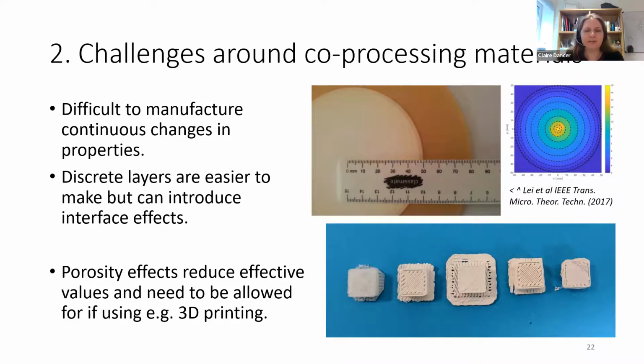And the porosity effects that we get in materials often lead to reductions in their allowable effective values. If you're doing something like 3D printing, these are some 3D printed ceramic composites, you get a lot of porosity. Unless you're going to work a lot at post-processing, which probably eliminates why you were doing the 3D printing in the first place, you need to think of these materials as actually containing quite a lot of air in that structure.